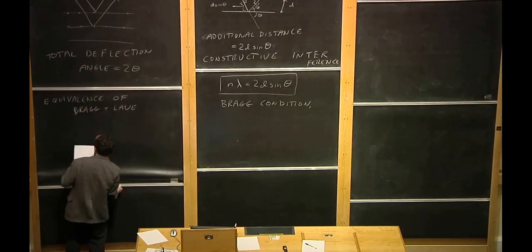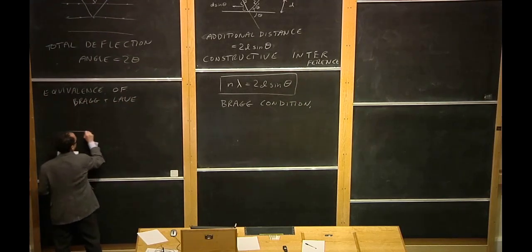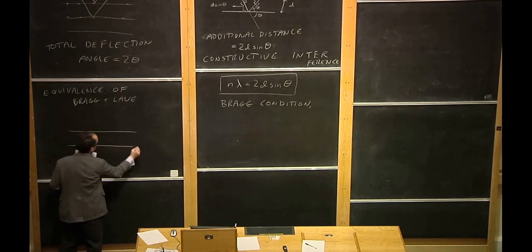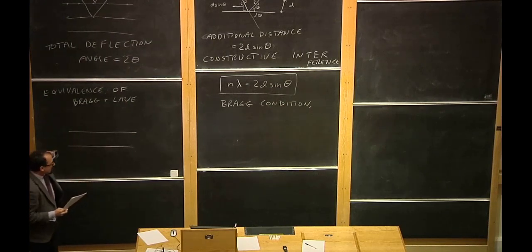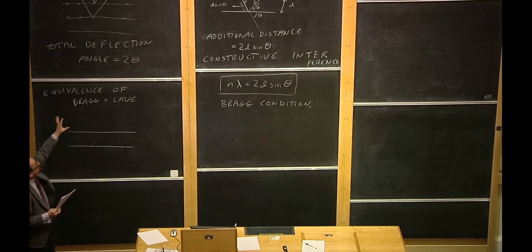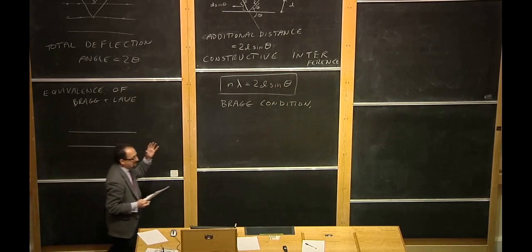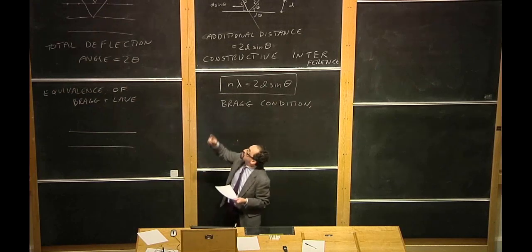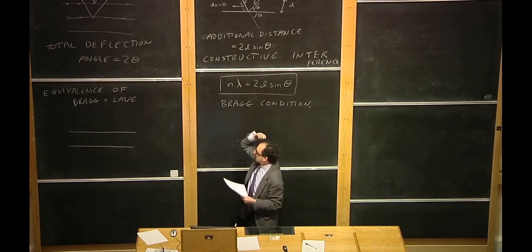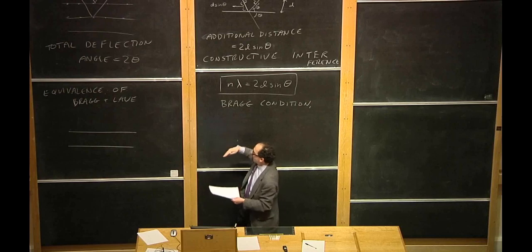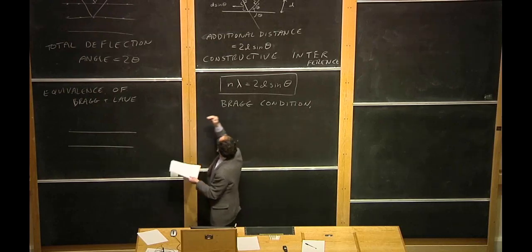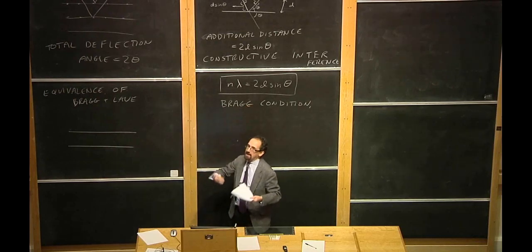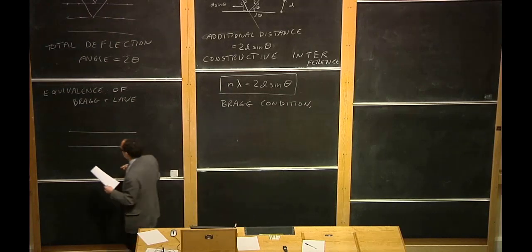Okay, so same diagram. We have two parallel planes in a family of lattice planes. You can kind of understand why these two are going to be related. Remember from last lecture that reciprocal lattice vectors are associated with families of lattice planes. So that G up there is going to be telling you something about this family of lattice planes. The fact that we have parallel planes is because we have a reciprocal lattice vector. Those are sort of equivalent statements.